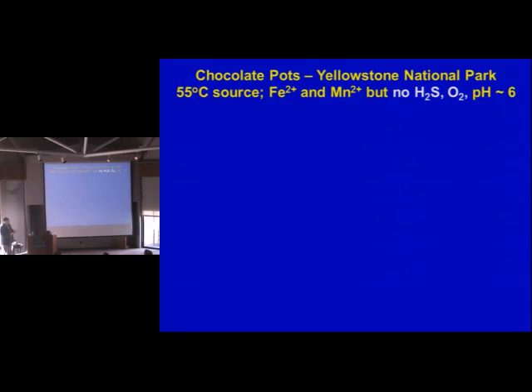Now I'm going to show you some items about Chocolate Pots. First of all, the source is 55 degrees C typically. There's plenty of iron and manganese. There's no hydrogen sulfide detectable and no oxygen. So that means at 3 micromolar oxygen, we don't detect it. At 0.1 micromolar sulfide, we don't detect it. So this is an iron and manganese-rich groundwater, but it's hot, or at least relatively hot. Since I study the vents, this is actually warm.